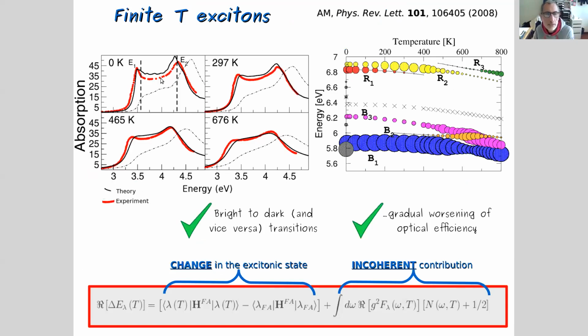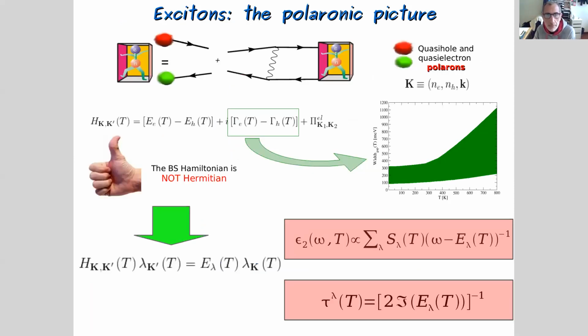If you do that, your absorption experiment will actually depend on the temperature, because the more you populate the phonons, the more you increase the temperature, the more the width of the electron pairs will increase. And you can prove on a piece of paper that if you increase the temperature enough, the Bose factor in the theory will give a linear explosion with temperature. Of course, above a certain temperature you have anharmonic effects entering the story, and then everything gets more and more complicated.